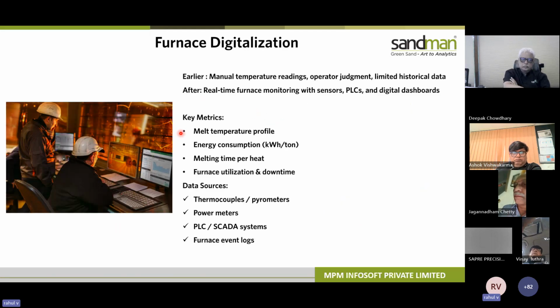Furnace digitalization. Earlier, there were manual temperature records, operator's judgment, which is very subjective, and limited historical data, because all data is written in notebooks, and we only measure it, let's say, once in 15 minutes or once an hour. Now, with real-time furnace monitoring with sensors, we get data almost every second, every minute, every hour in our hands with PLCs and digital dashboards. The key metrics here are the melt temperature profile, which is very crucial as it decides the viscosity and a very wide range of defects, energy consumption, melting time per heat, furnace utilization, and downtime. The data sources over here are thermocouples, pyrometers, power meters to understand how much energy is being consumed, PLC or SCADA systems, and furnace event logs.